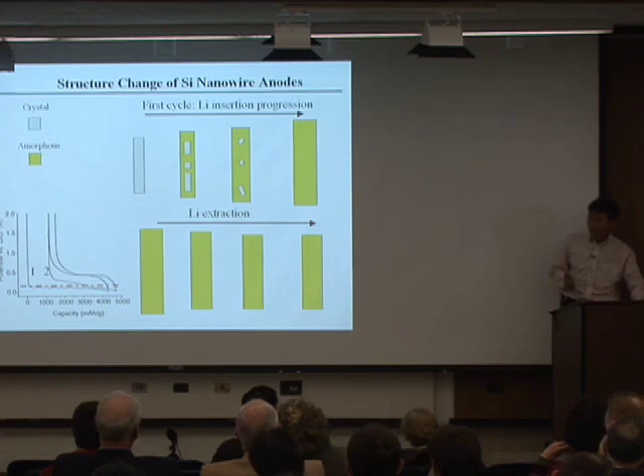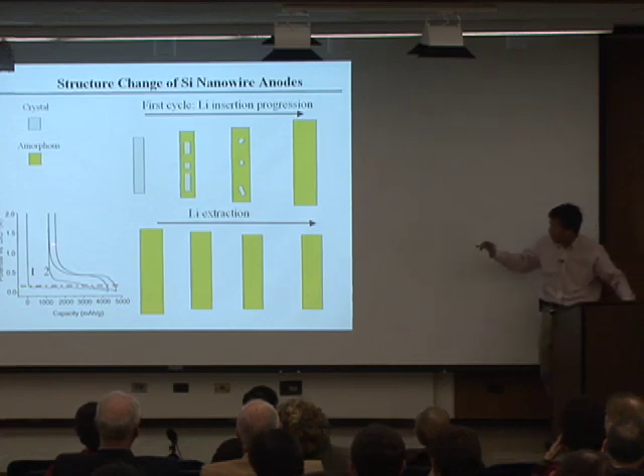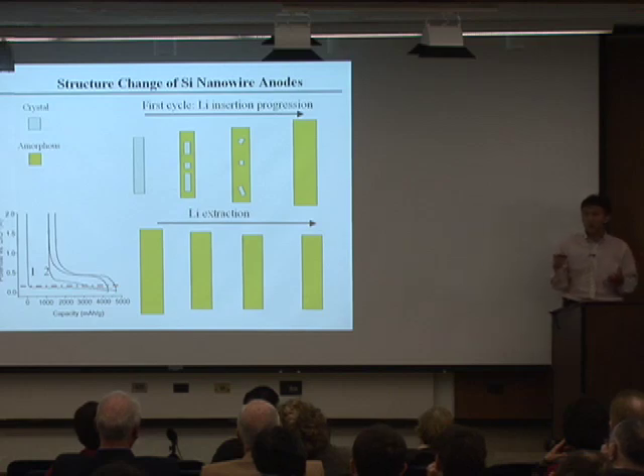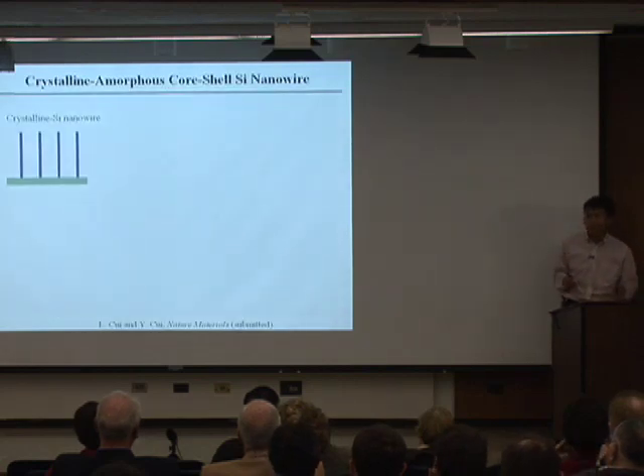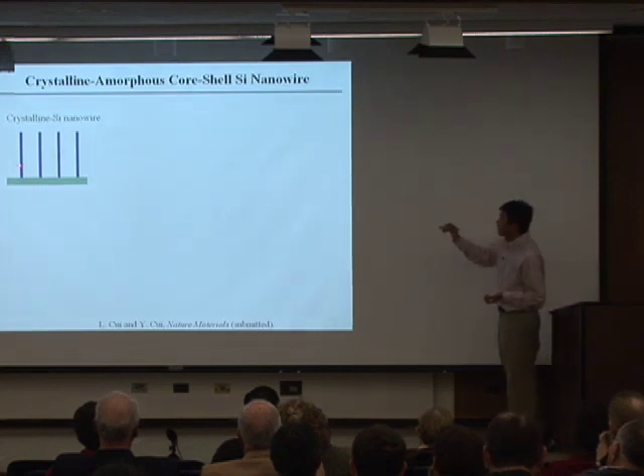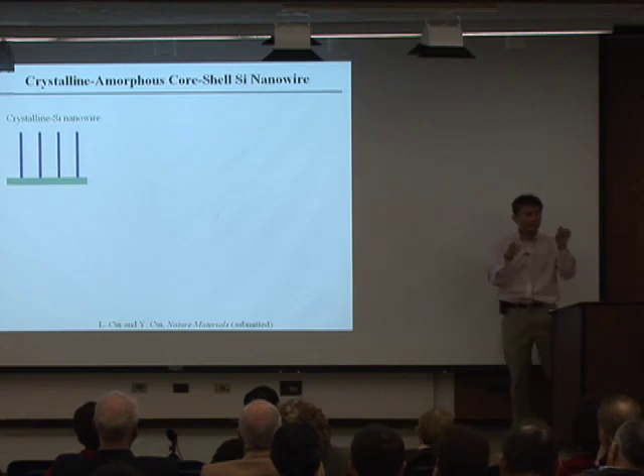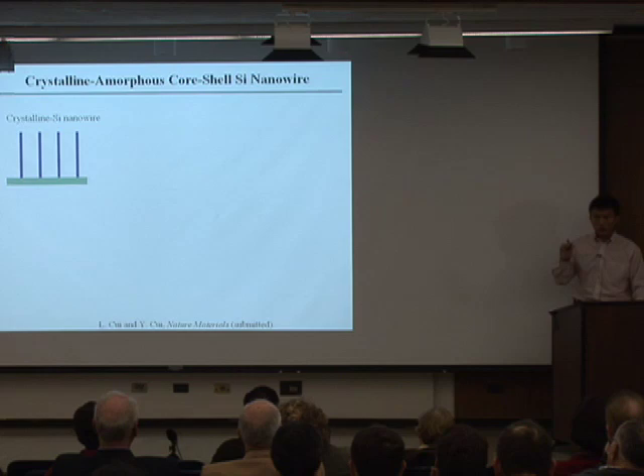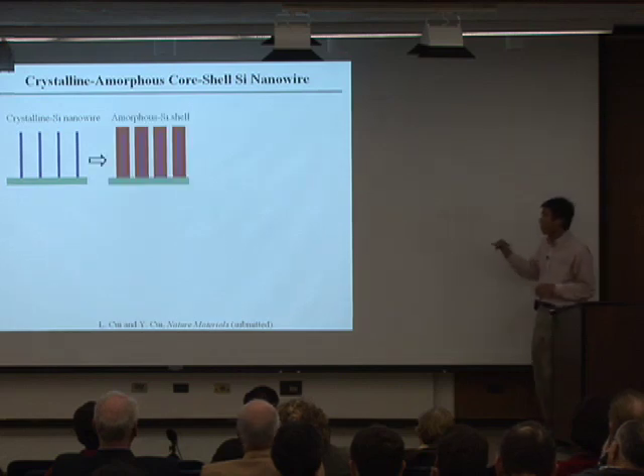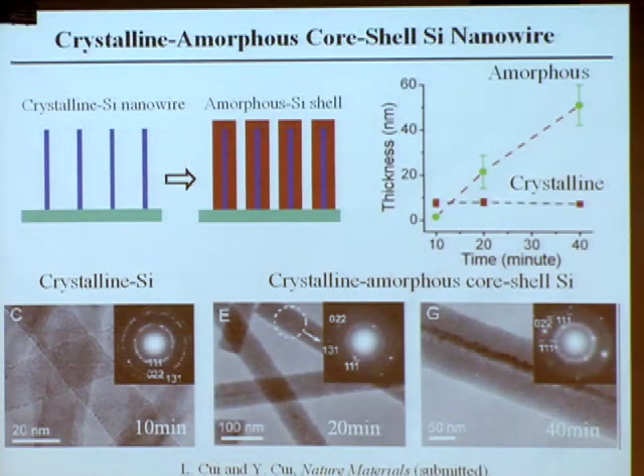So we decided to test this idea, and when we charge up the batteries, we only charge up to this potential, to see if we can make amorphous shell and crystalline core nanowires. So we decided to do it. We made a single crystal nanowire by nanoparticle catalyzed growth. After that, we changed the growth condition a little bit to deposit amorphous silicon, indicated by the red color, on the surface of the single crystal core. We have done extensive study to show that this is the single crystalline nanowire in the core. These are the amorphous shell.